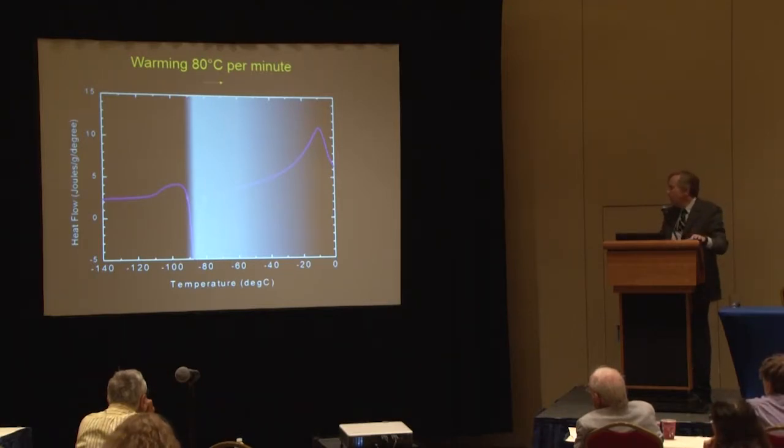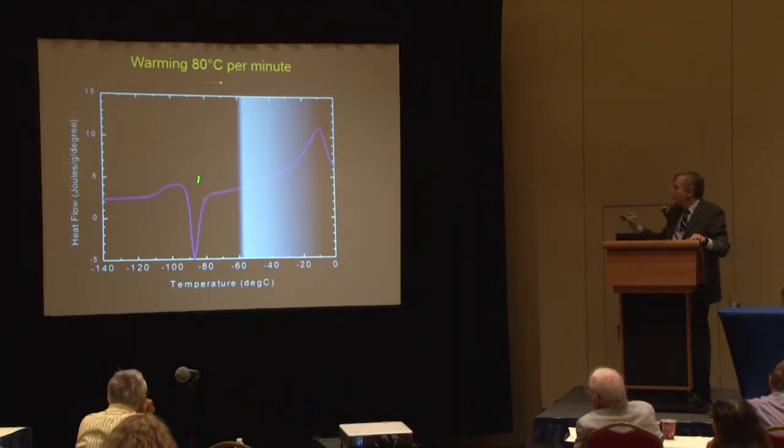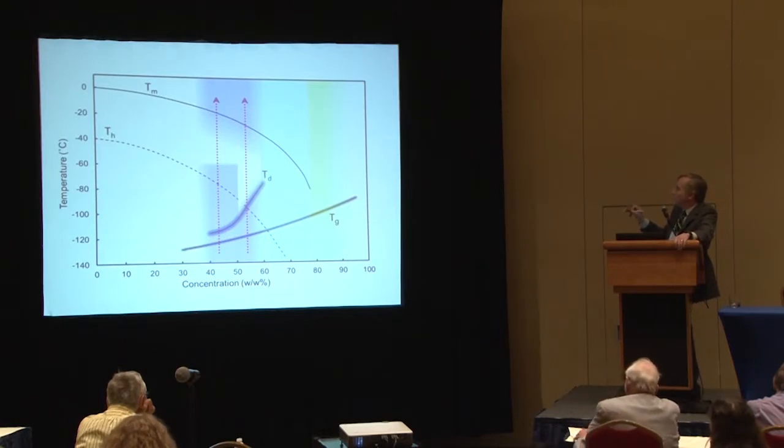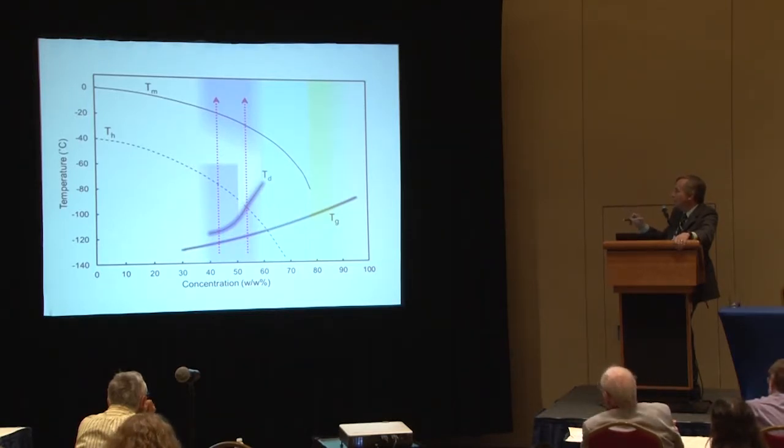But amazingly, they found that at some other concentrations, calorimetric devitrification occurred, but this devitrified solution would remain optically transparent and not turn opaque until warmer temperatures were reached. And if they plotted these results on a phase diagram, what they found is that solutions that were just barely vitrifiable would exhibit delayed opacity when you rewarmed them.